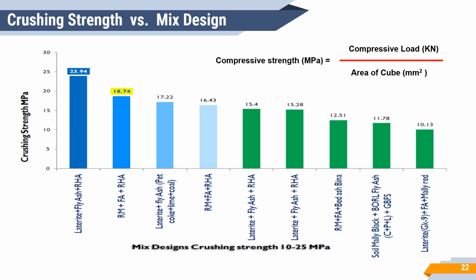The use of mixed raw material facilitates the availability of alumina and silica for faster reaction in alkaline medium. For example, red mud is mixed with fly ash and rice husk ash, and the geopolymer matrix has shown about 19 megapascal of crushing strength. The input of fly ash does not suffice for easy availability of silica in view of the presence of quartz instead of amorphous silica. The requirement of amorphous silica for alkali activation reaction is achieved by the input of rice husk ash.